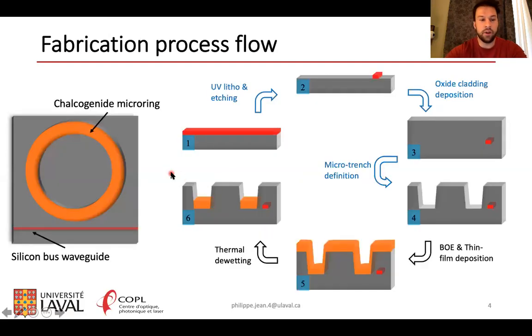So our hybrid integration method consists of embedding a chalcogenide microring inside the oxide cladding of the silicon on insulator platform and using a silicon bus waveguide to couple light to and from the microresonator by evanescent coupling. So if we look at the process flow right here, the first 4 steps are done in foundry. So starting from a standard SOI wafer, the silicon structures are defined by UV lithography and etching. And then there's the oxide cladding deposition, which is pretty standard.